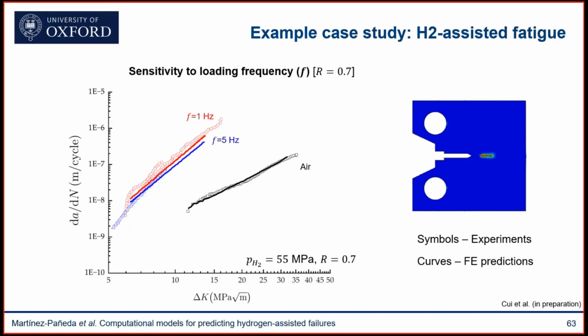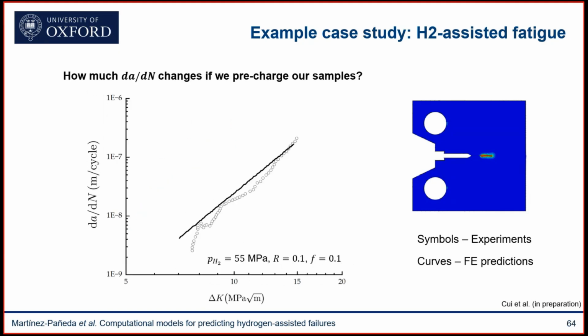We change the frequency, we change the load ratio, not touching any of the parameters of the model. There's no fitting here whatsoever. Again, a very good agreement. So this gave us confidence that the model is very robust and is working very well. So we were quite excited about this ability of the model to blindly predict the different scenarios, changing loading frequency, pressure, and load ratio.